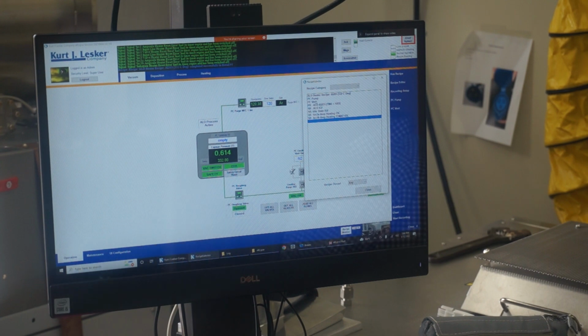With this, per cycle, you build one monolayer. You can't have another monolayer unless you have another cycle. That one just builds and builds and builds, it piles on. Here, two precursors react, one monolayer. Two precursors react, second monolayer.